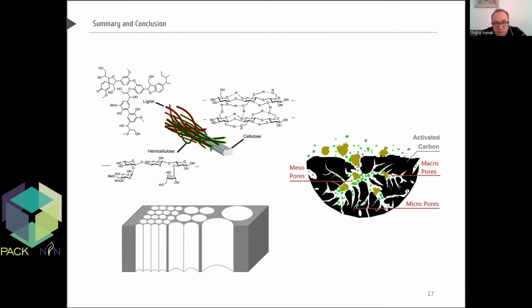The first one is that the carbon yields of the biomass differ according to the chemical and elemental compositions of the precursor, which were in the range of 5 to 50% by weight.